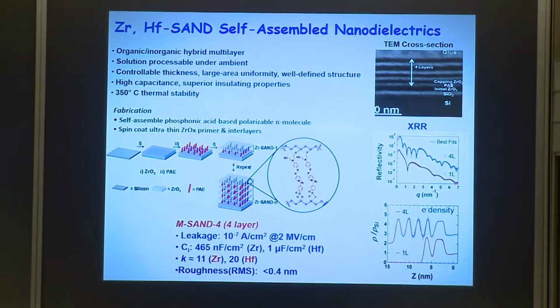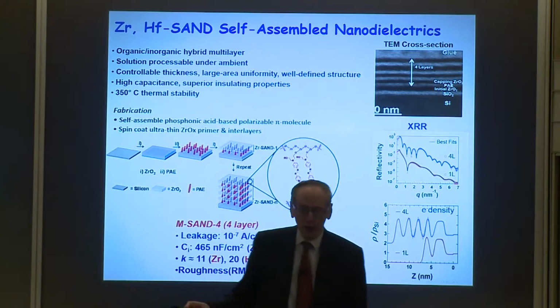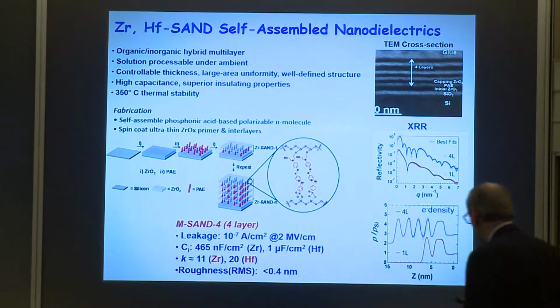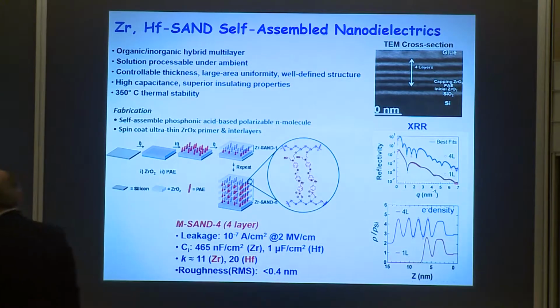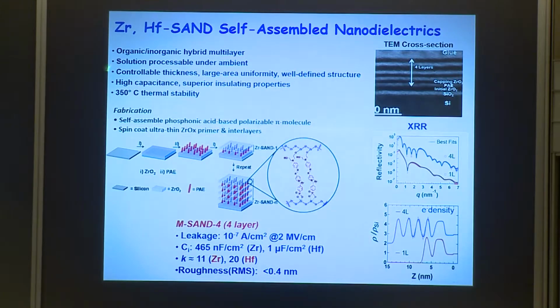And you might say, boy, you've drawn a cartoon. How do you know you really have something like that? So here's cross-sectional TEM. This is just showing the self-assembly process. So it's Howard Katz, Bell Labs, zirconia layers, and then this stilbazolium type phosphonic acid group. So you build up layers. You usually build up 4 layers is enough. They're stable to 350 C. Really quite inert to most solvents.